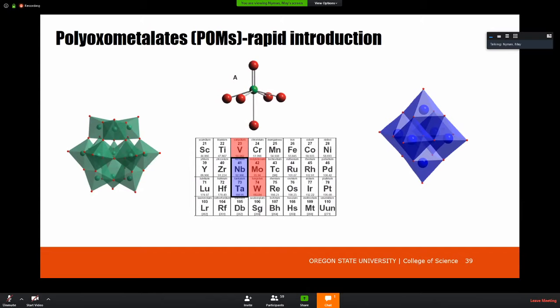Okay, so we monitored the pH, and mind you, we're not adding acid or base. This is just the pH that is controlled by protonation or deprotonation of this cluster as it undergoes whatever chemistry it's doing. And so the black is our standard, just tetramethylammonium decaniobate, which is completely neutral. Now, when you throw in alkalis, the pH rises to about 8.5 or 9, so it goes up to mildly alkaline conditions, and it just stays there.